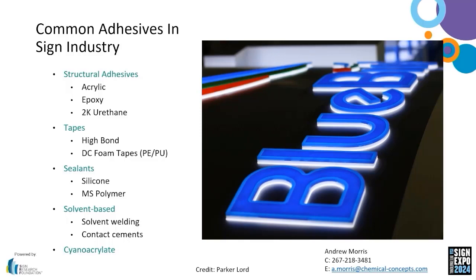Those adhesive tapes will continue to wet out, and you might hear me use that term, wet out. What's happening is that those tapes have some elasticity to them, and there's micro cracks in the metal. You could think of that elastic adhesive as having almost tentacles, like an octopus, and it's slowly flowing into all those micro cracks. So typically over, let's say, 3 days, you'll get to say 90% strength, and it can take up to weeks for those high bond tapes to get to full strength.